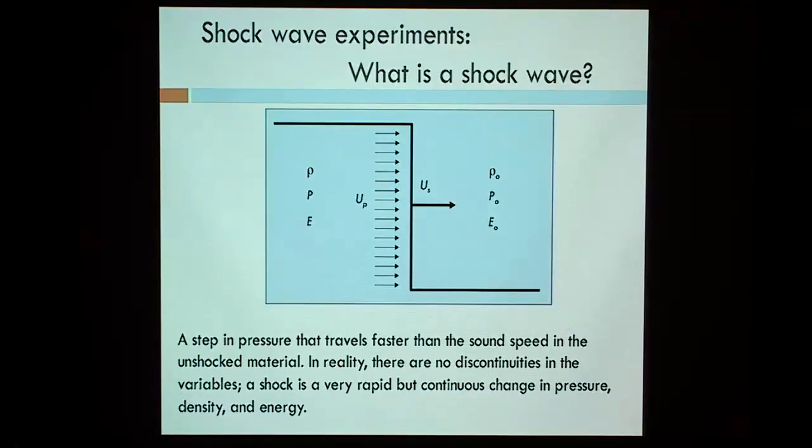Okay, so here's a cartoon of a shockwave. We have some unshocked material at some initial density, initial pressure, usually one bar, effectively zero, and some initial internal energy. Okay? We have a nearly discontinuous step in pressure, which is traveling into that material at a velocity u sub s, the shockwave velocity, which is larger than the sound speed in this material. That makes it a shock.